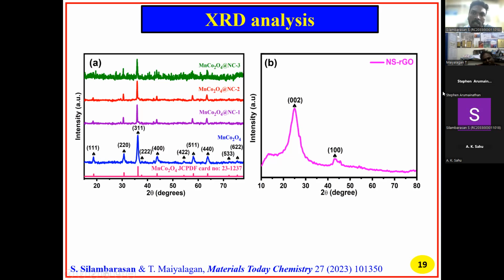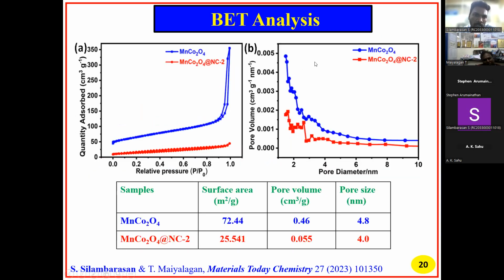Then, figure B is the XRD pattern of NSRGO, around 25 for the 2 theta value. The plane is 002. This NSRGO we use for the negative electrode of the device. Next, the BET analysis: for MnCo2O4, the surface area is 72, and then for the composite material it is 25.